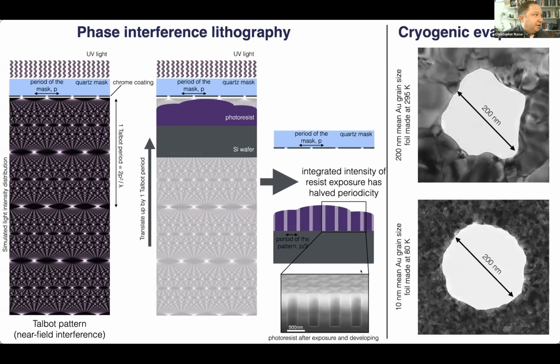And then the other key thing that we had to develop was a way to make thin foils of gold that had crystals that were smaller, because if you put a thin layer of gold down in a typical evaporation, you end up with crystals that are of order hundreds of nanometers in size.